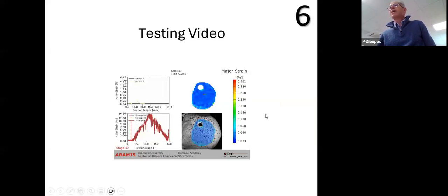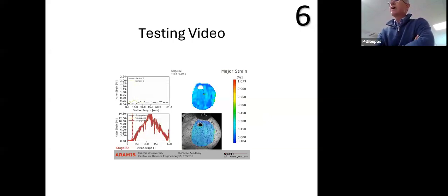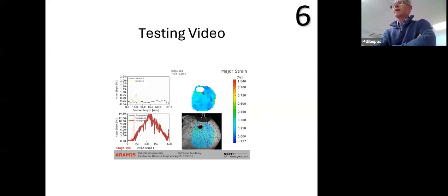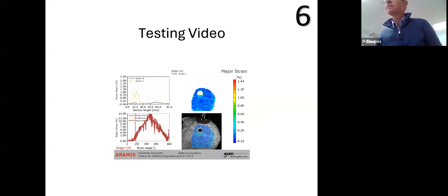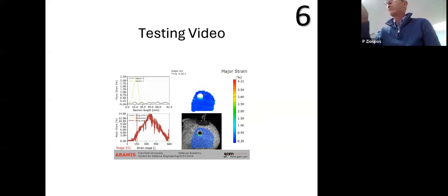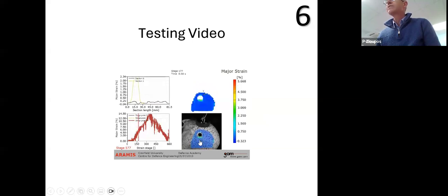Let me see if that plays. Oh, be nice. Okay, there you can see it happening now. So there is a strain map image of the skull. The strains are on the right-hand scale. There's the impactor, has come down now and hit the skull. You can see the strain building up around the circular hole, on that side of the hole. There's the impactor coming down. Here you can see the maximum strain building up still, right? The strain here is still building up.